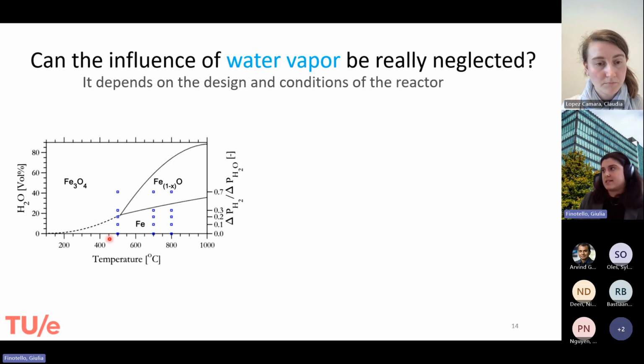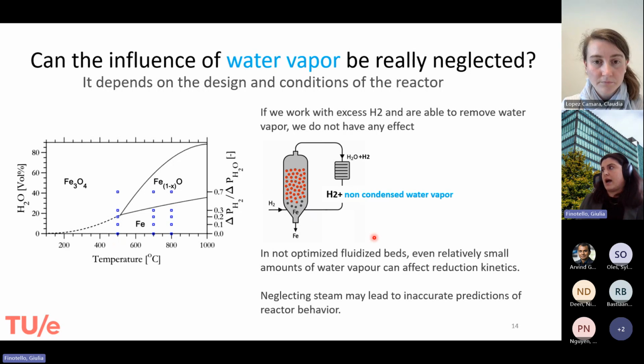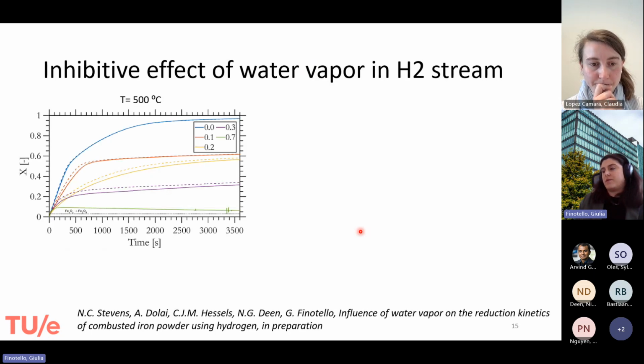And so that tells us something, of course, that if we are able to remove the water vapor, if we work with excess hydrogen, we're doing things correctly. But if, for example, we recirculate back our hydrogen and water vapor stream, and we don't do this in a good way, and we therefore reintroduce some water vapor, well, it means that we didn't optimize our fluidized bed, and even a small amount of water vapor can have an effect on our reduction kinetics. And that's indeed what we have seen with other TGA.